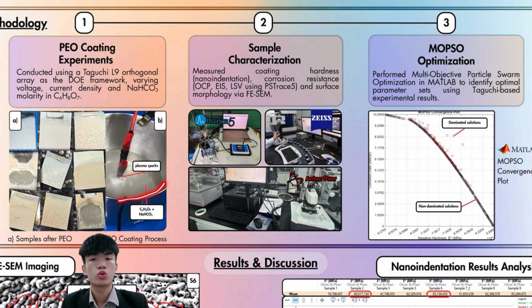The aluminium 7075 samples in this case acted as the anodes, and the Taguchi design of experiments was used to systematically reduce the number of trials needed, where a total of 9 trials were needed, with varying voltages ranging from 300 to 400 volts. For current density, it ranged from 0.5 to 1.5 amperes per centimeter squared, and for sodium bicarbonate concentration from 0.1 to 0.4 molarity.